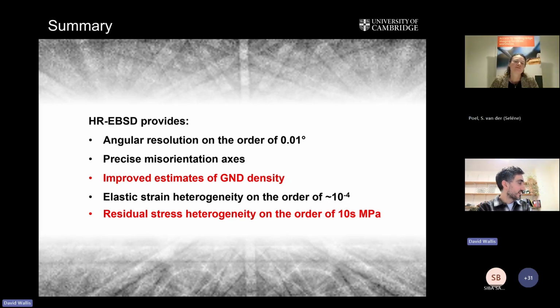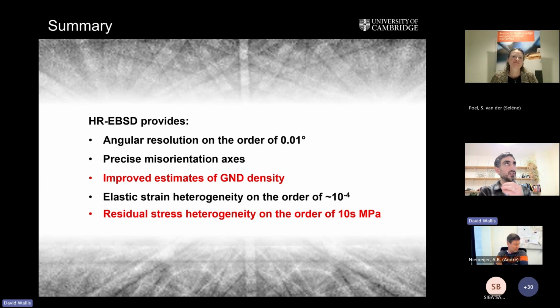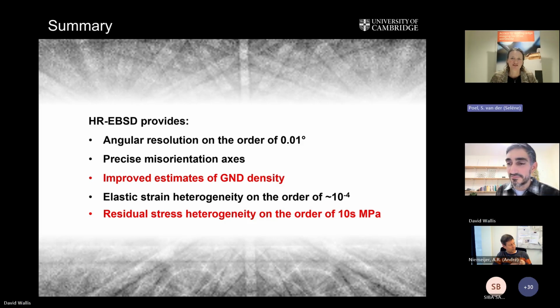One of the things that helps with this is that on the EBSD detector there are additional detectors. There are little diodes, the forescattered electron diodes, and they give you a complementary image of the sample, and they're really good at showing up the scratches. So if you crank up the contrast on these other detectors, you can make sure you're not looking at scratches and getting artifacts, and you're really looking at the deformed crystal. Right, okay. So you have ways of making sure that you are looking at the right thing. Great.